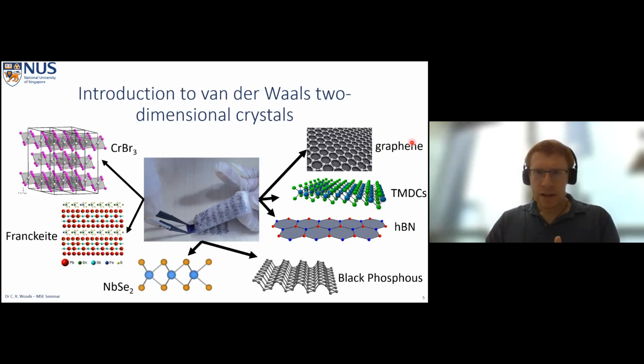And all of these, this is not an exhaustive list at all, but I chose these ones because on the screen at the moment, what you can see is a lot of different material properties. So in graphene, we can quite reductively call it the metallic or conductor. Transition metal dichalcogenides, the direct gap semiconductors in their monolayer form. So they have very strong light matter interactions. So here's our optical properties. Hexagonal boron nitride is the wide gap insulator. So it's a dielectric layer.